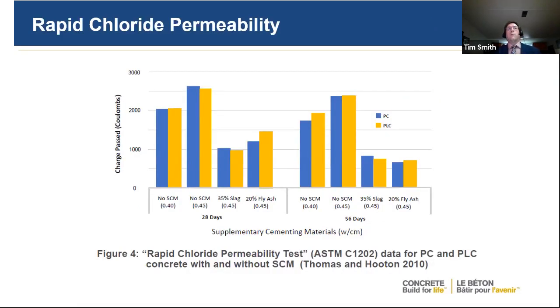If we want to look at rapid chloride permeability, that's the ability for the chloride to penetrate into the concrete itself, you'll see that both the Portland limestone cement and the Portland cement are performing very well, very close to each other, basically within the standard deviation of the tests that were done.